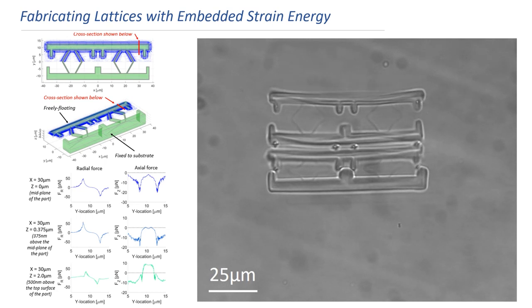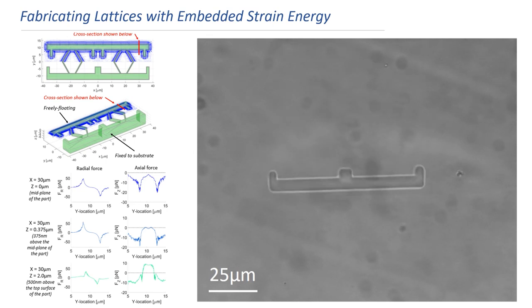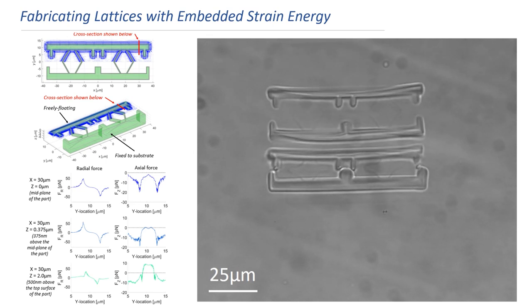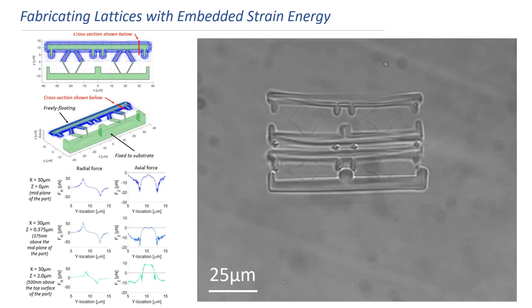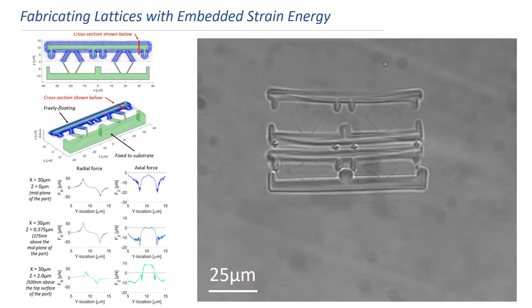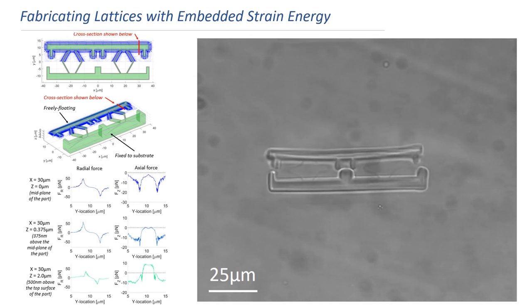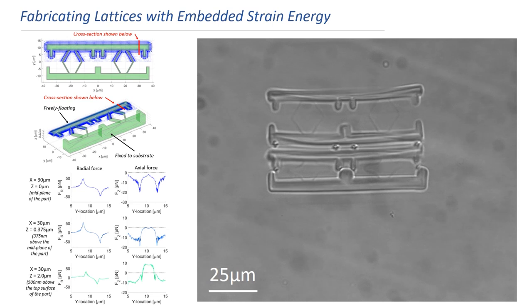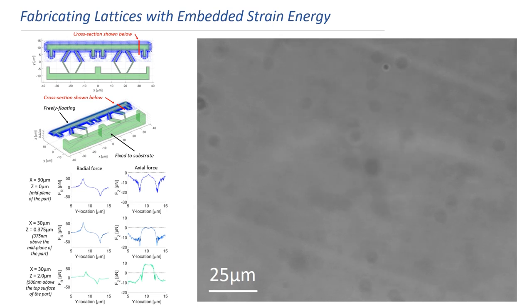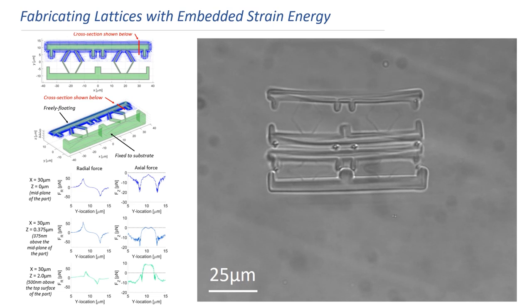My group wrote a code that is available on my website that allows users to upload CAD models of designs that they would like to print and then optically trap. The code calculates the best locations to place optical traps on the uploaded parts so that the strongest and most optimally placed optical traps can deform the 3D printed structure as desired. This video shows our system printing a microstructure that is then optimally deformed by optical tweezers until its beams store the desired amount of strain energy in their geometry and then the system glues the structure fixed in its deformed configuration. Multiple layers are printed with embedded strain energy in this way to create a metamaterial that if impacted would cause the glued portions to break via shearing so that the bent beams would rapidly release their stored energy in response to the impact load.